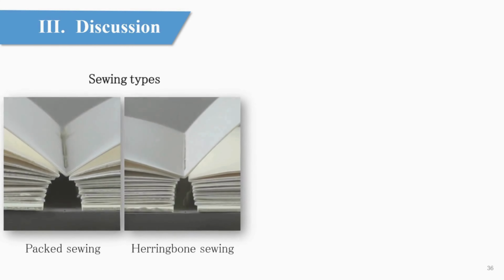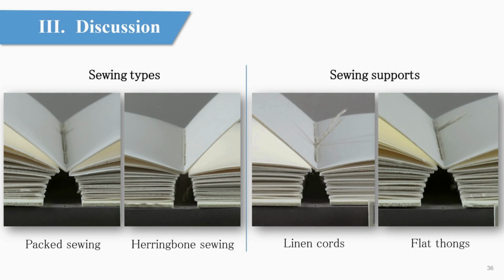The tests on models carried out by the conservation studio have allowed us to refine the interpretation of the material tests. Pack sewing appeared to be the most suitable for creating a wide spine arc. This confirmed data from the literature, in particular the fact that it stiffened the sewing support. Herringbone sewing, on the other hand, produced a tighter, more angular arc. We can presume that this effect can be modified by the combination of herringbone sewing and flat thongs.